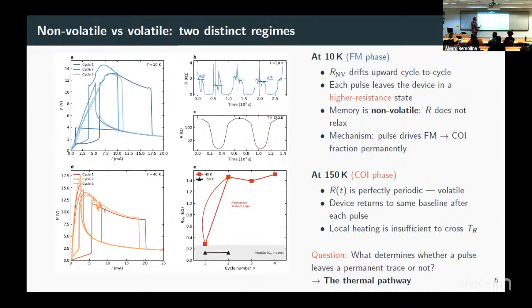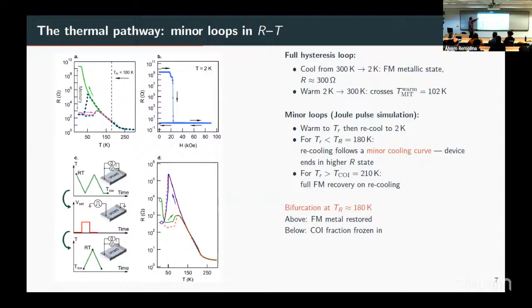Here is a bunch of cycles of IVs, and here I'm plotting the local resistance as a function of time, okay? And there is a region at high temperature where this doesn't happen, so it doesn't have a memory effect, but the resistance does change. So basically, this is what I'm calling non-volatile and volatile memory. So this material has both behaviors. I can induce a regime where the sample will remember at what temperature it was fired, and there is a region where it doesn't remember, it just changes, okay?